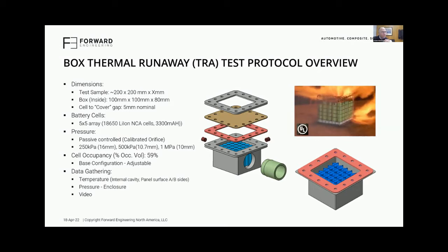temperature range. As you'll see in the data results, a 16 millimeter orifice runs you about 250 kPa plus or minus. And because again, we have 100% state of charge cells in there, 25 cells of known chemistry, they're going to deliver a certain amount of energy when they're run into thermal runaway. We repeat that test 3 times. We evaluate temperature, pressure, and monitor with high-def video, which I'll show you, to observe how the panels perform, how these materials perform. Get into a little more detail here real quick.